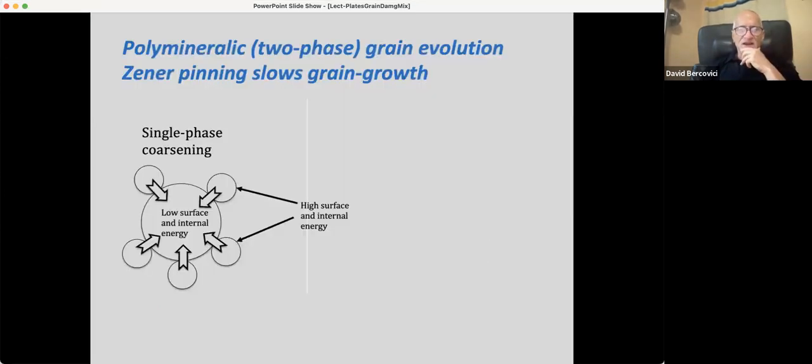So what happens in grain growth? Okay, here's my silly cartoon where I just, of course, treat grains like spheres. If I have a big grain surrounded by small grains, the small grains have a high surface tension to them because of their large curvature, and they wind up squeezing their mass into the bigger grain. So the big grain eats the small grains.